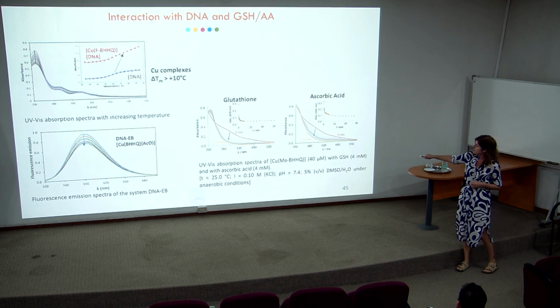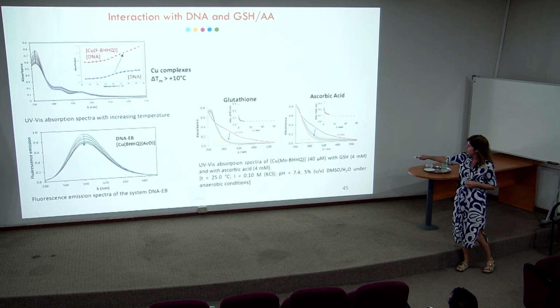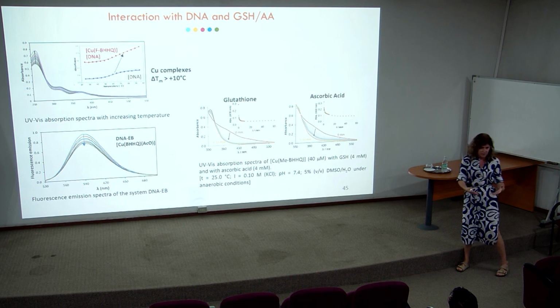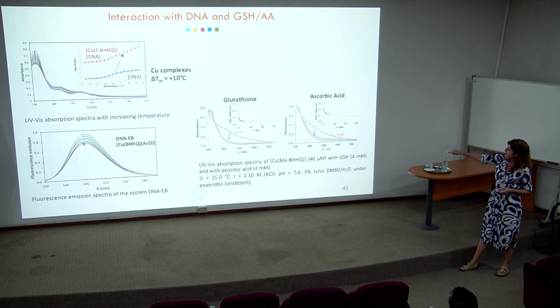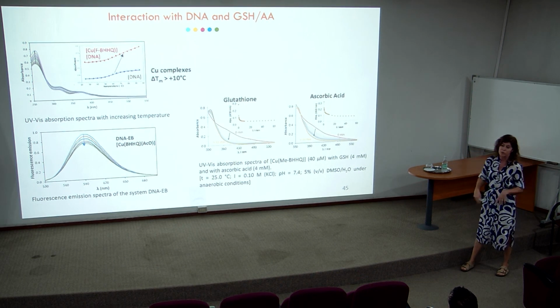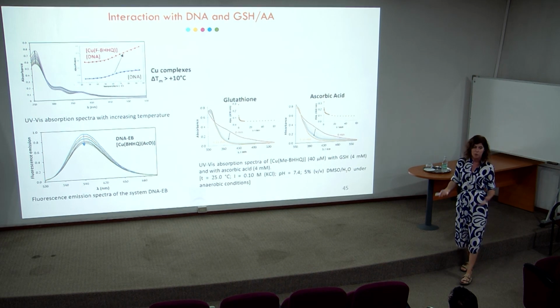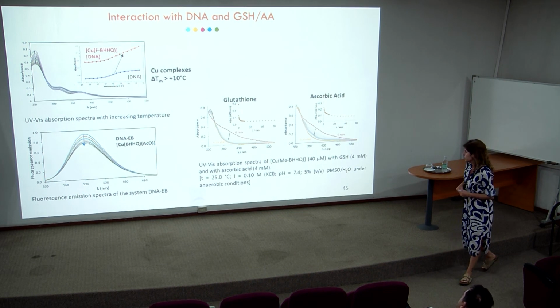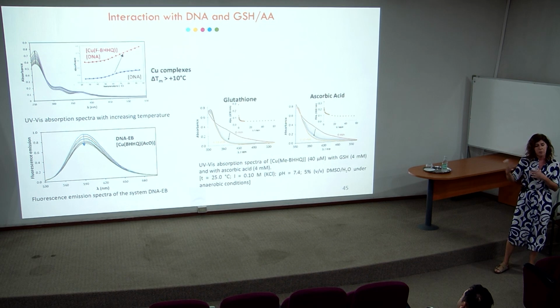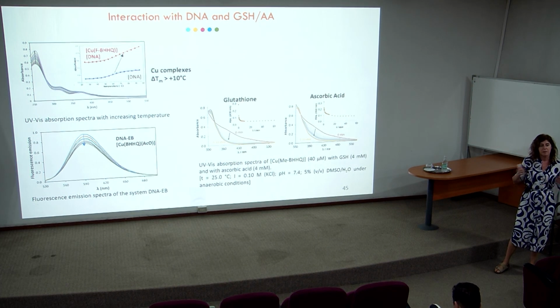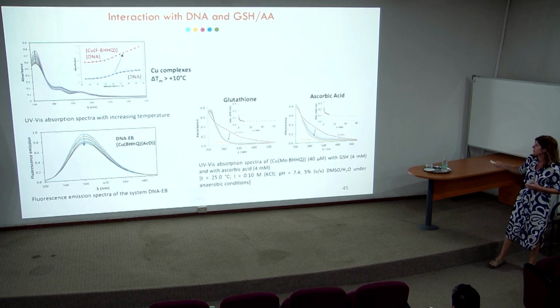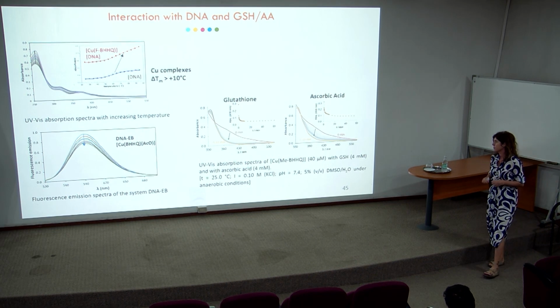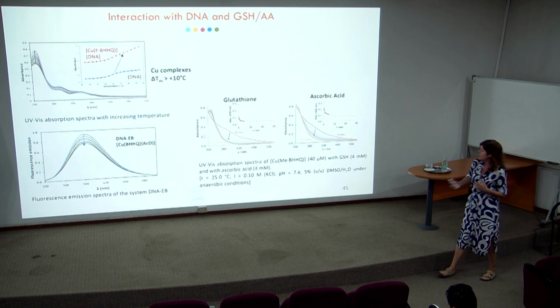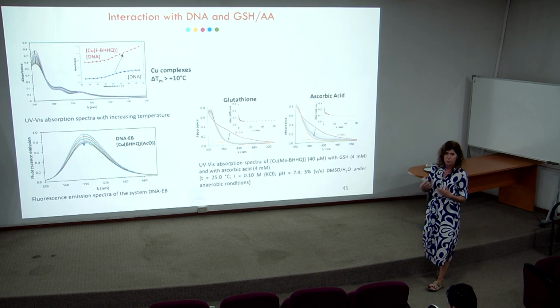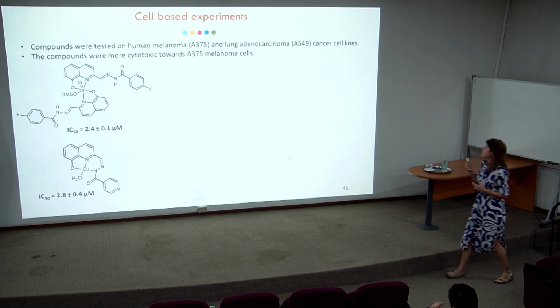And we could see the disappearance of the charge transfer band of the complexes. This last spectrum corresponds to the spectrum of the free ligands, so we could conclude that the compounds were reduced from copper 2 to copper 1, and the ligand was released upon interaction with glutathione or ascorbic acid. So the reduction of the complexes seemed to occur in solution.